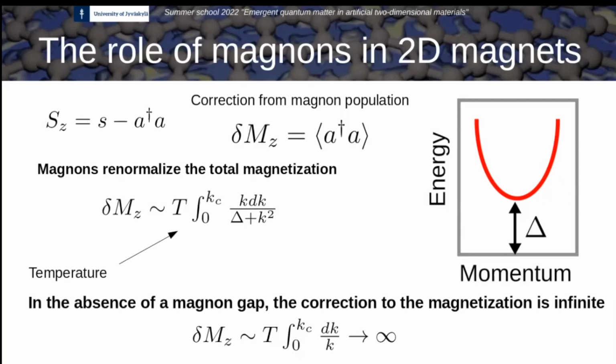How is it that you have magnetism with in-plane magnetization if you are kind of violating the Mermin-Wagner theorem? That is a very good question. The answer is that when you have in-plane magnetization, the Mermin-Wagner theorem actually breaks down, because it assumes that you have local interactions, interactions that are local in space and decay very quickly as you go far from it. But if you have in-plane magnetism, then you have dipolar interactions, and dipolar interactions have a very, very long tail.